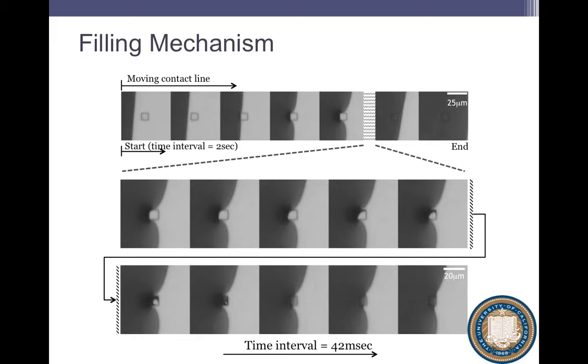What happens in filling is you have this ink that is dispensed onto this roll, and the ink front is spreading to cover the roll. And ideally, it's filling the features that you've etched into that roll. So we built this printer, and we still use it, it's instrumented like crazy. It has high-speed cameras everywhere, lots of measurement capability everywhere, just so that we could understand the physics of gravure. And so here's a series of snapshots out of one of those cameras, and you can see an ink front approaching an isolated cell. That's a cell that's etched into our cylinder, and the ink front is approaching it. And it approaches it, and we notice something interesting. When it reaches that corner, it actually pins right at that corner.